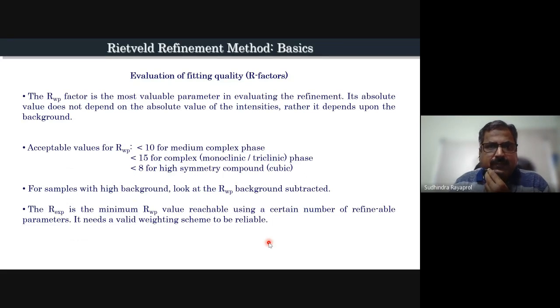And how do you evaluate the fitting quality, or R factors? What are the acceptable values? RWP is the most valuable parameter in evaluating the refinement. You should always keep an eye on the RWP value rather than on chi-square. Chi-square up to 5 or 6 is acceptable if your RWP is less than 10. For medium or complex samples, RWP should be less than 10. For very complex or low symmetry systems where you have overlapping peaks, it can contribute to high values of RWP. For high symmetry systems like cubic, it should be less than 8. That is the ideal condition.